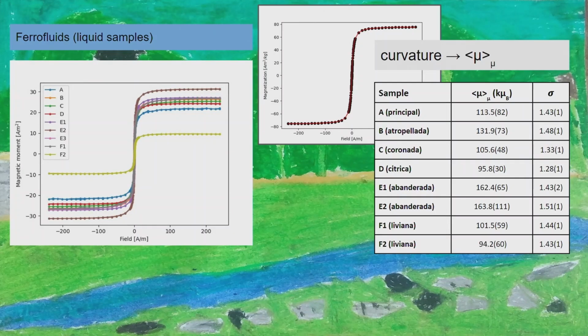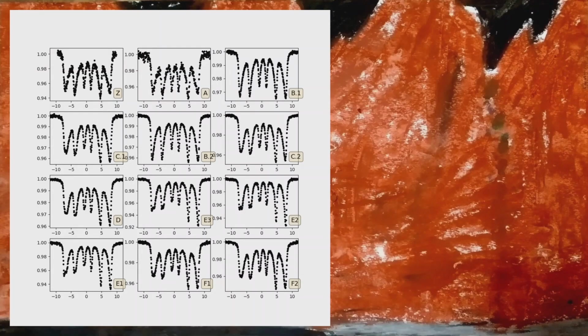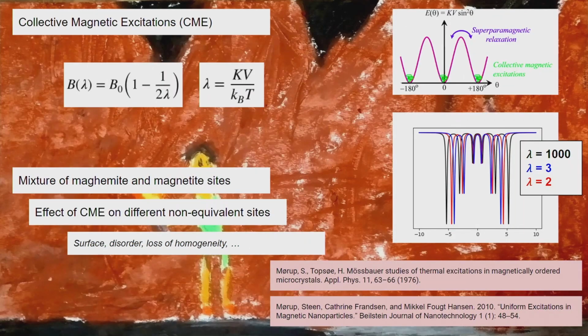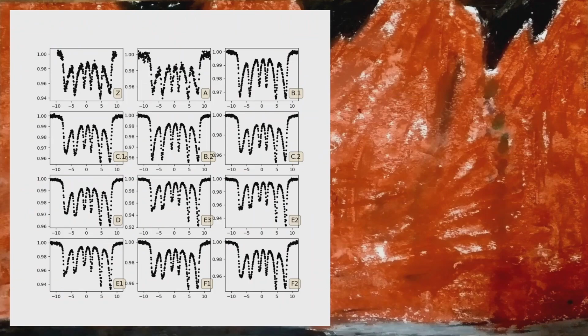And from ferrofluid, you have good information about the magnetic moment, weighted by magnetic moment, or the mean magnetic moment. I like more the information weighted by magnetic moment, that is like weighted by volume. Okay. And here we have the different Mössbauer spectra. You can see that they are almost the same, but with very, very different features. So how can we understand this difference?